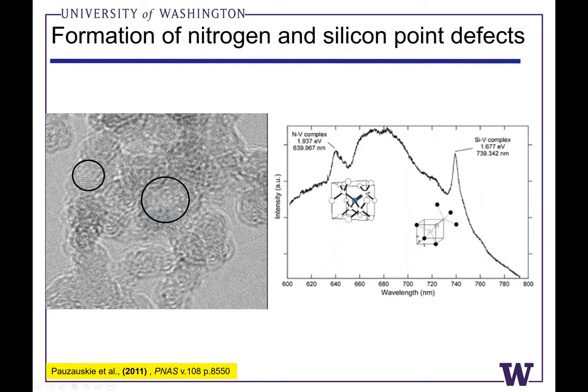And we wanted to characterize these diamonds further with, say, Raman spectroscopy. So we started to collect Raman spectra, but all of a sudden we started to see very bright luminescence from these diamonds that we were really concerned about. We thought maybe we couldn't get diamond Raman, that the photoluminescence was just too bright.